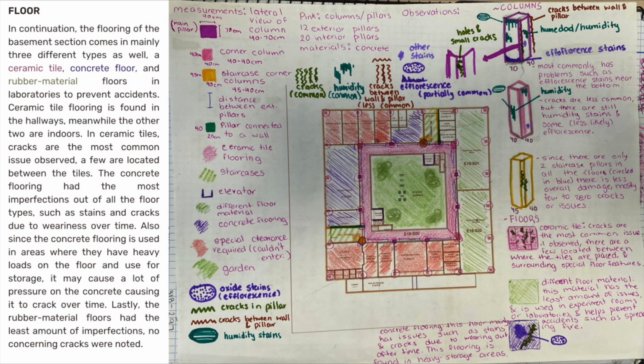The concrete flooring had the most imperfections out of all the floor types, such as stains and cracks due to weariness over time. Also, since the concrete flooring is used in areas where they have heavy loads on the floor and used for storage, it may cause a lot of pressure on the concrete, causing it to crack over time. Lastly, the rubber material floors found in laboratories and classrooms had the least amount of imperfections. No concerning cracks were noted.